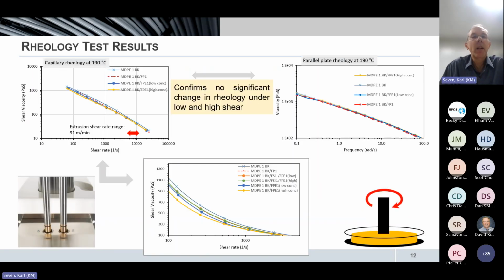So here, I'm not going to talk a lot about this, but we did look at some rheology tests for these samples. I'm showing both high shear rheology test results that were conducted in a capillary rheometer, top left, versus lower shear ranges tested in a parallel plate rheometer. We did not see a lot of significant shifts in viscosity in this comparison. We did note slightly lower viscosity in the capillary rheology results for the sample with the higher concentration of the polar polymer additive, but overall, these differences were quite small.